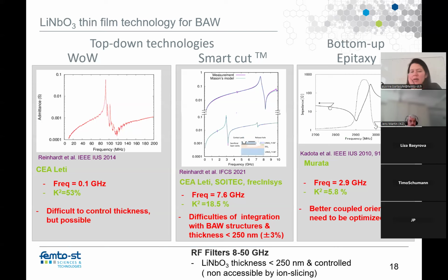So if you look, well, it's an old slide. I put this here to show that in 2014 people were already trying to do polishing for the filters, when at that time they badly controlled the thicknesses. That's why you get a lot of ripples here, because of bad control of the thickness. Now it is done much better. So basically with single crystalline films, I think 300 nanometer thick or 250, I don't remember, which come from SOITEC, we attained 7.6 gigahertz with an electromechanical coupling of 18.5.